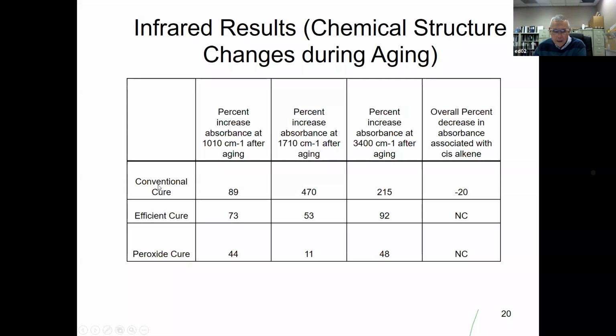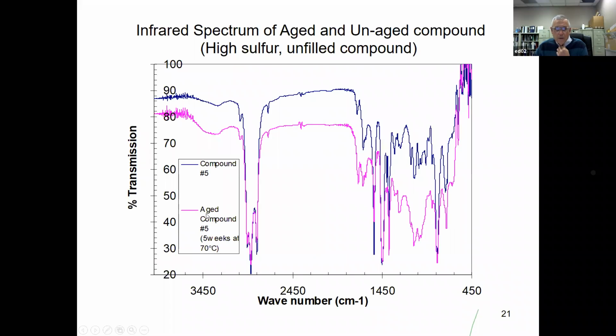You can see that the conventional cure has a much greater change than the efficient cure and the peroxide cure. So somehow sulfur is accelerating the oxidation. We also see a cis-trans rearrangement in the conventional cure, which we don't see in the efficient cure and peroxide cure. Here we show the infrared spectra of the conventional cure before and after aging, 5 weeks at 70 degrees C. We see the increase here associated with the hydroxyl group, the increase here due to the carbonyl, and this broad peak here, which we say is associated with sulfoxide, peroxide, ether, and epoxide linkages.